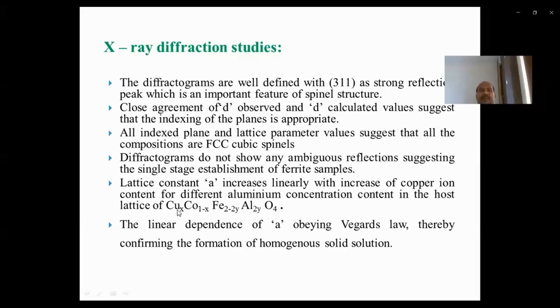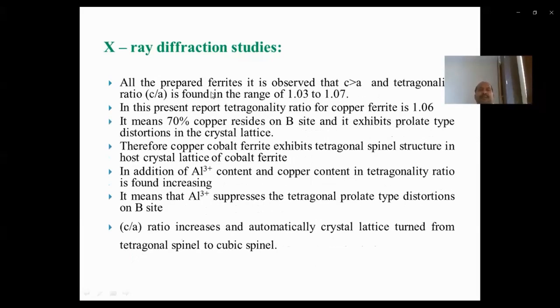The lattice constant increases linearly with increasing copper ion content for different aluminum content in the host lattice. This is the formula for the preparation of these ferrite samples. The linear dependence of a confirms the formation of a homogeneous solid solution. In all the prepared ferrites, c is greater than a, and the tetragonal ratio c upon a is found to be in the range of 1.03 to 1.07. In the present report, the tetragonal ratio of the copper ferrite is 1.06.